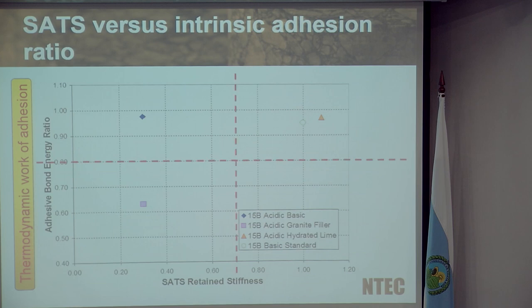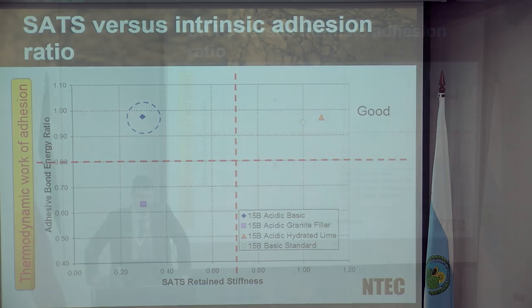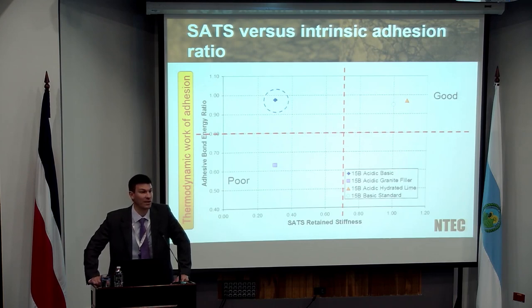If I put all the little graphs up here, we've got a range of different types of performance based on the SATS retained stiffness. So these are asphalt mixtures. This was actually field material. This was material that was cored out of particular road sections. And we've got different types of behavior. We've got very good behavior on the right-hand side, which correlates really nicely with the thermodynamic predicted intrinsic adhesion results and those energy ratios. We've got very, very poor behavior on that bottom left-hand quadrant, where the SATS results and field performance is indicating poor performance, and we're getting very, very low energy ratios from our thermodynamic surface energy calculations.